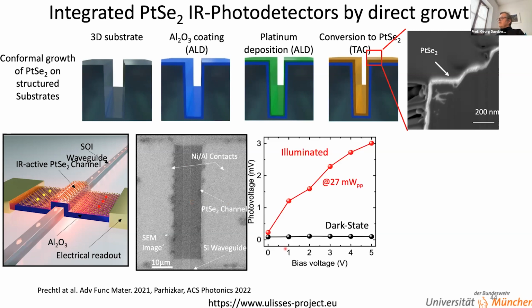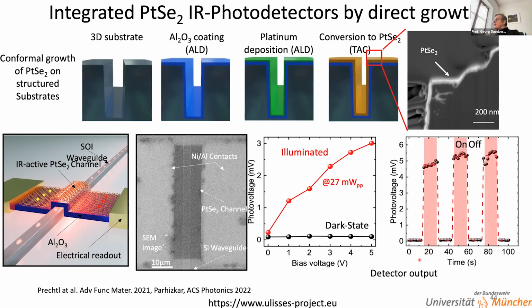Here you can see that we get some photovoltage out of it, and here's on and off switching with the detector output. It's not the best material. Graphene had shown better results, but the beauty is that we can integrate it. These were the first devices which we made, and we're pursuing this to optimize growth for this type of application.